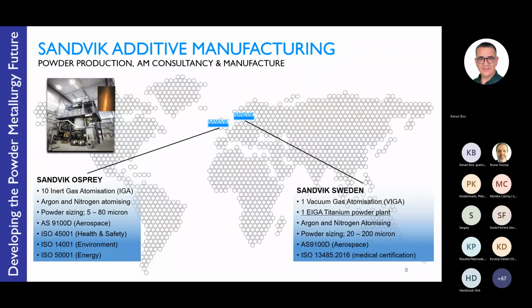In Sweden, there is a vacuum induction gas atomizing facility, mainly producing nickel-based superalloys, although it has the capability to produce various different materials, including copper alloys, and the electrode induction gas atomizing facility, which is dedicated to titanium alloys typically. Nitrogen and argon atomization. The powders typically are slightly coarser in terms of the average size distribution, from 20, and then coarser powders for applications like hot isostatic pressing. And this facility is AS 9100D Aerospace approved, and also has some medical certification for the titanium powders.